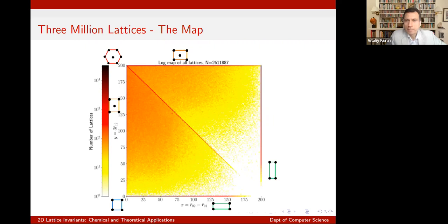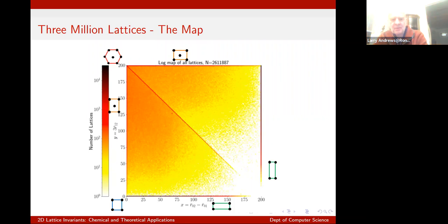So if I could extend a little bit of what Roy said, what you see is in part just bias in the way the crystal structures are reported. For instance, centered tetragonal lattices can always be done as either face-centered or body-centered, but the body-centered is always the one that's chosen, except in very rare cases.